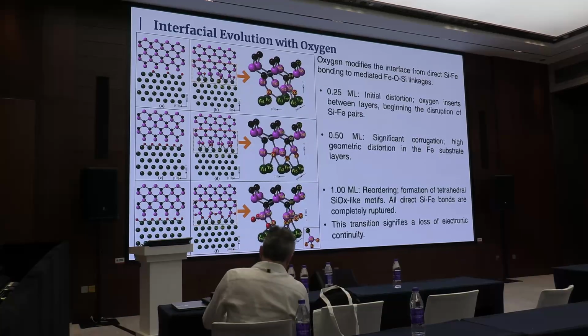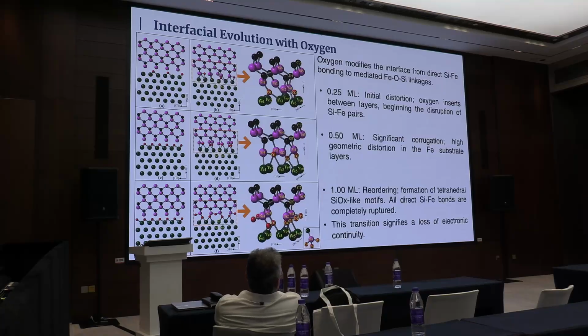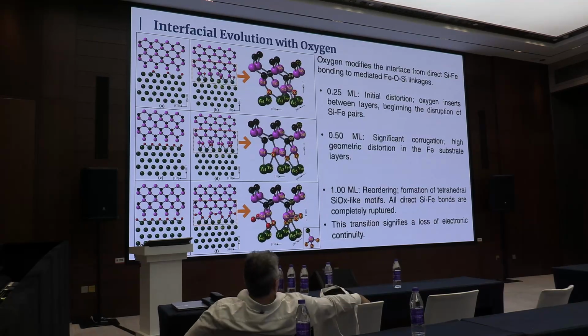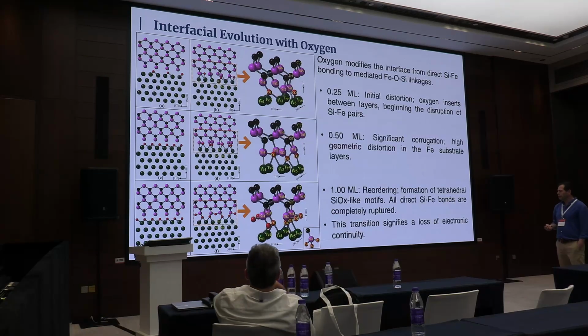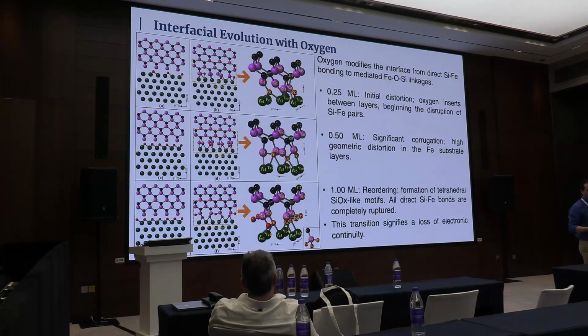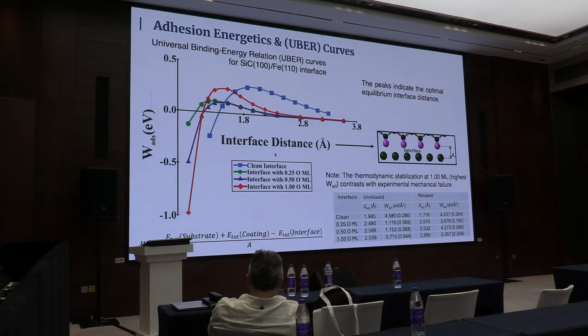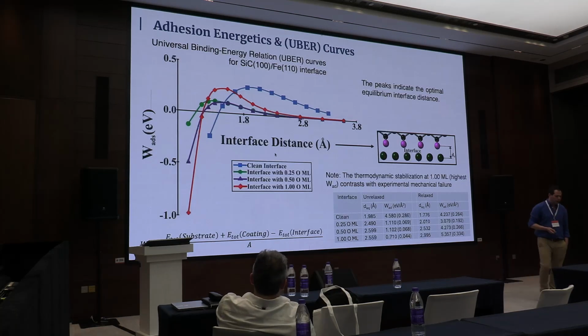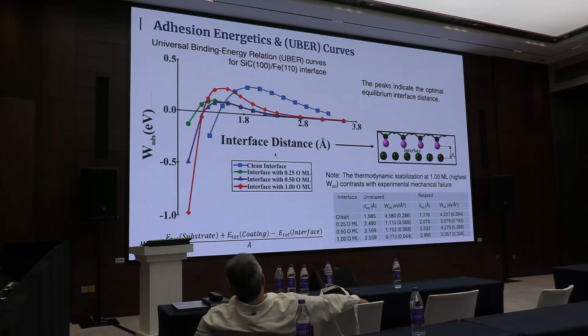This also confirms that our model is representing well the other system that is more realistic. So we have not an amorphous but a crystalline one, and we have pure iron there, but the effect is not transmitted to the other sides of the material. It's just located at the interfaces. So now we make a first idea of how strong these interactions could be as soon as we start to increase the concentration of oxygen.